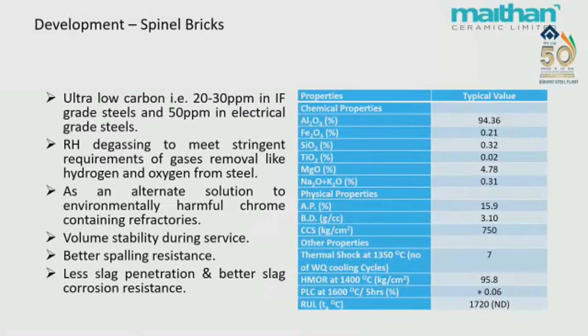Then the next parameter we are looking into is the volume stability during service, so better spalling resistance and less slag penetration. So all those, on the right side, you will see what Maithan has developed, the spinel refractory bricks with the typical values or typical properties as shown in the graph.